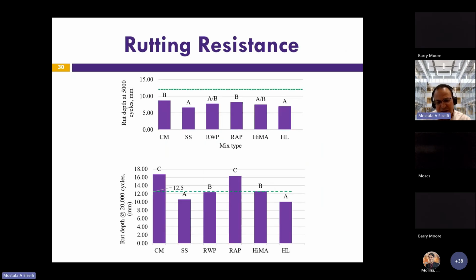If we look at the rutting, you can see that at 5,000 passes, all the mixes passed, which is the top figure here. You can see that all of them had a rut depth less than 12.5 millimeters. However, at 20,000 passes, we started seeing differences between the mixes. Again, the control mix and the RAP mix had the highest rutting. On the other hand, the steel slag and the hydrated lime had the lowest rutting. And in between, we had the recycled waste plastic and the HiMA, which was below the 12.5 millimeter. So it means that they passed this factor.